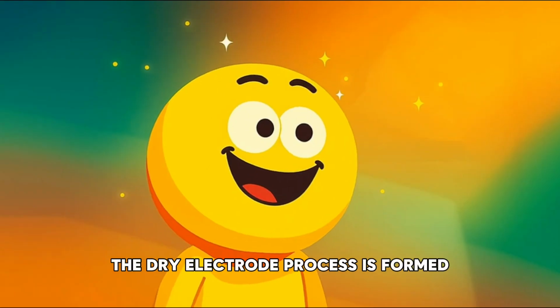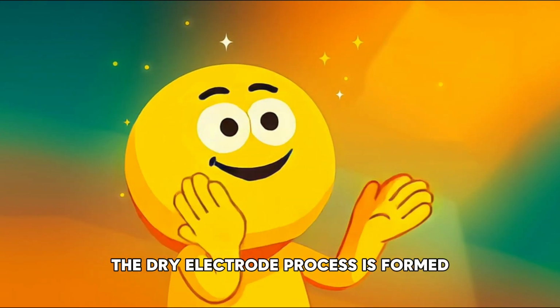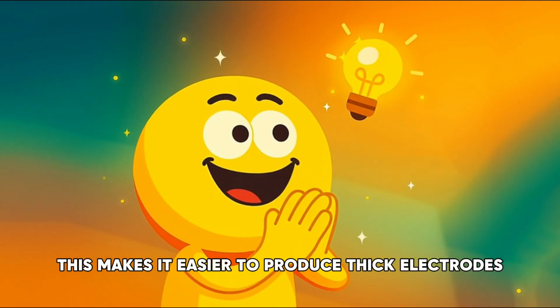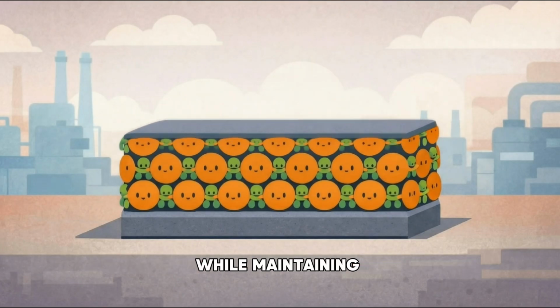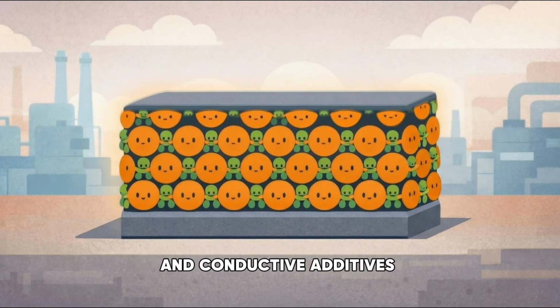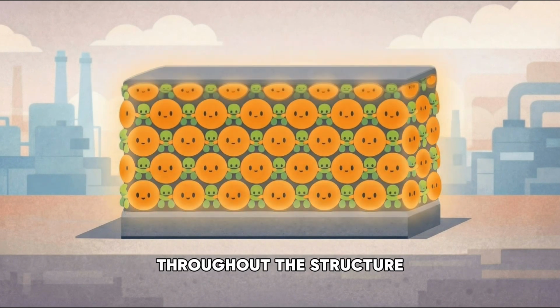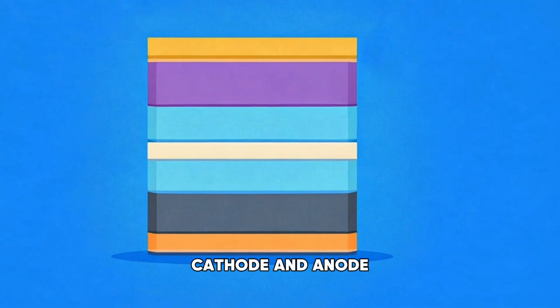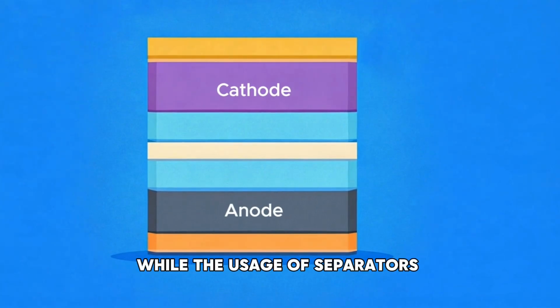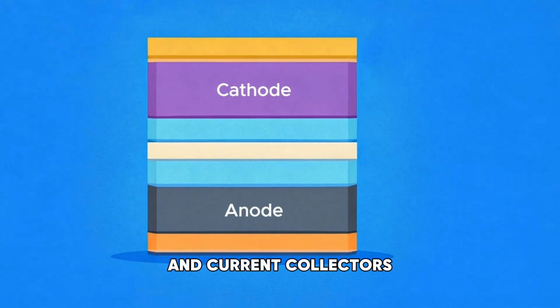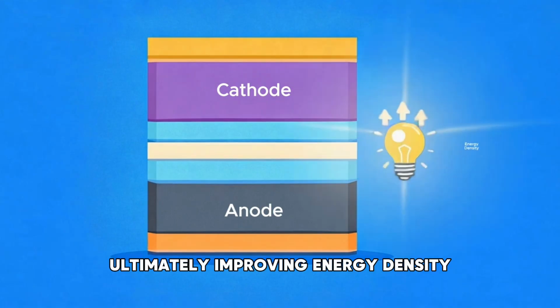In contrast, the dry electrode process is formed entirely in the solid state. This makes it easier to produce thick electrodes while maintaining uniform distribution of binders and conductive additives throughout the structure. As a result, the proportion of cathode and anode material can be increased, while the usage of separators and current collectors can be reduced, ultimately improving energy density.